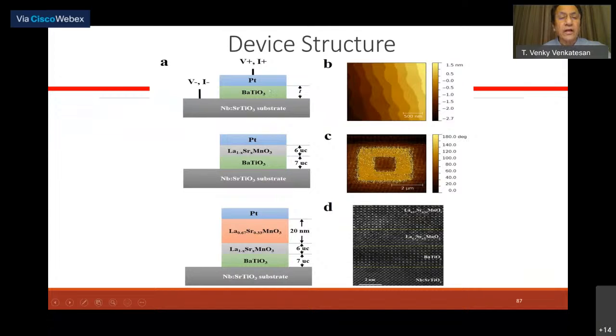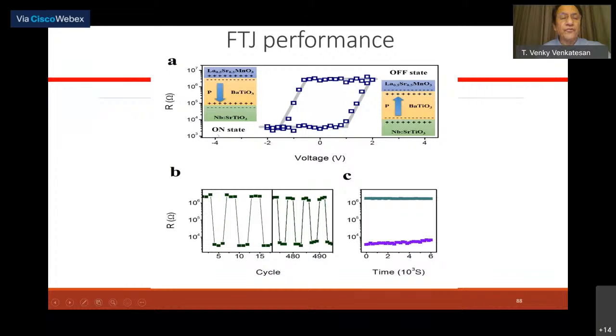Now, in between the barium titanate and the top electrode, I can introduce different oxide layers. We introduced LSMO, where the lanthanum strontium composition is varied, so you can create different LSMO layers. So you can create many interfaces, and you can see the entire structure is a coherent, single crystalline structure that you created here. And this is typical FTJ performance. You see resistance versus voltage. What you see is that the device is switching at a certain point. There's a saturation voltage, hysteresis, switching down and back again.